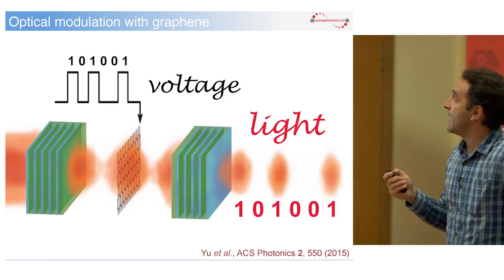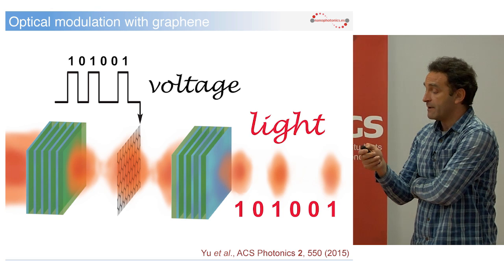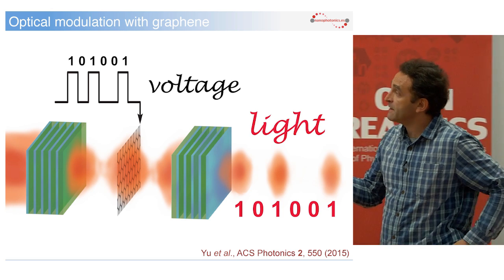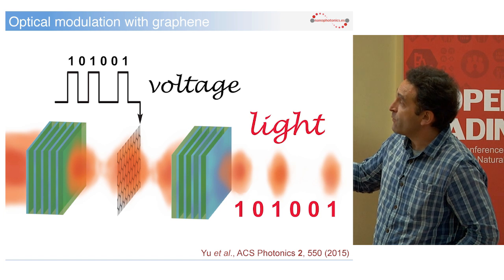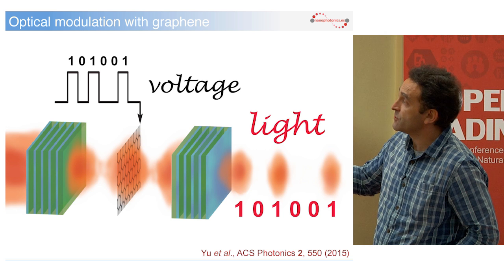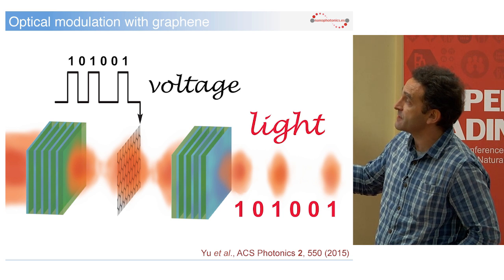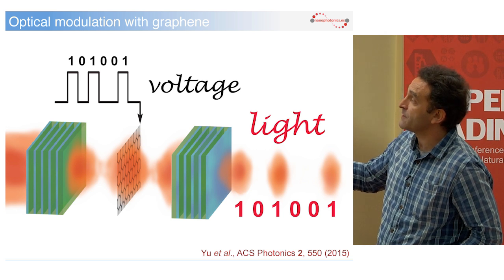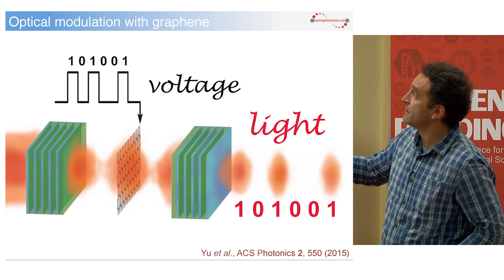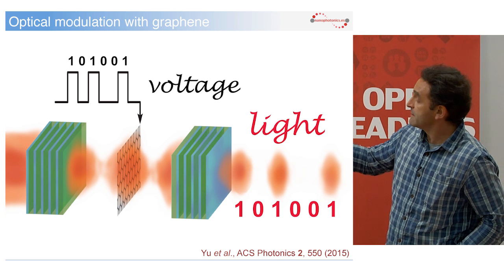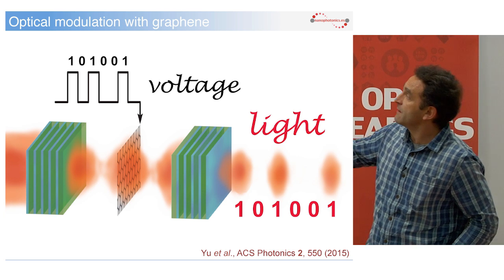Okay. Then another thing that needs to be commented on is that you have electrons that are evolving inside the partially occupied band. So these are intraband transitions, but you also have, if the photon energy is large enough, interband transitions. You can promote one electron from here to here. So interband, intraband. Okay? Your plasmons live in the region.